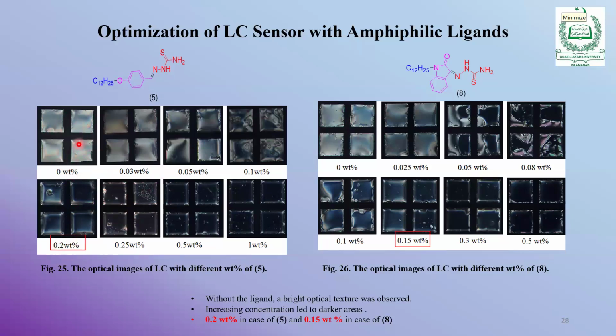You see the pattern or the texture is different. It is bright. When we add the ligand, it is slowly going to disturb the texture. Means the liquid crystal is now being perturbed by the presence of the amphiphilic ligand. And here, 0.2 wt%, it is showing the dark texture, the dark image. Means that homeotropic alignment is now being formed. You see here, you see the liquid crystals alignment.